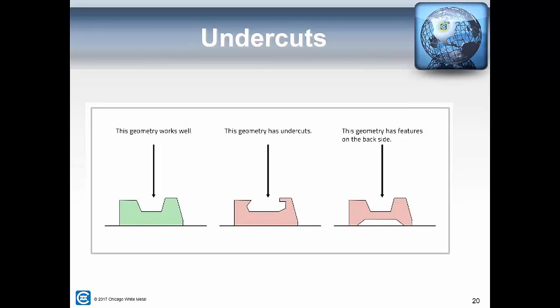Here are just 3 pictures that show a good representation of undercuts that are sometimes found in initial part geometries. As shown on the far left picture, there are no undercuts. Everything is drafted really well from the parting line. The middle image, you can see on the top portion, there are 2 kind of hooks, and as the part would try to eject off the half of the die, they would grab on and hold onto the die, so you wouldn't be able to functionally eject it. Maybe it would get stuck, or they would completely break off.